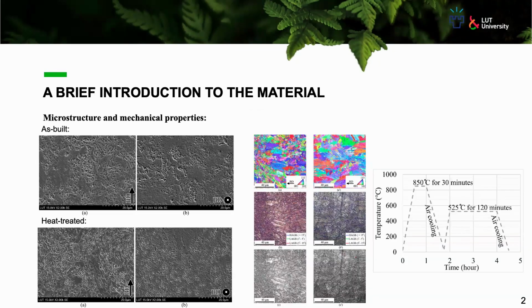Okay, so some of the results from our previous studies confirm the microstructure of this material after 3D printing as being martensitic, both in its as-built condition and even after heat treatment, the martensitic structure remains. However, after heat treatment, there is a slight difference between the texture and features, the size of the features in the microstructure. As you can see in these EBSD results, the left side is for the as-built material and the right side is from after heat treatment.